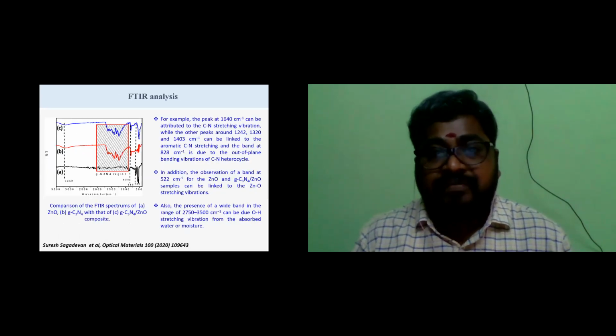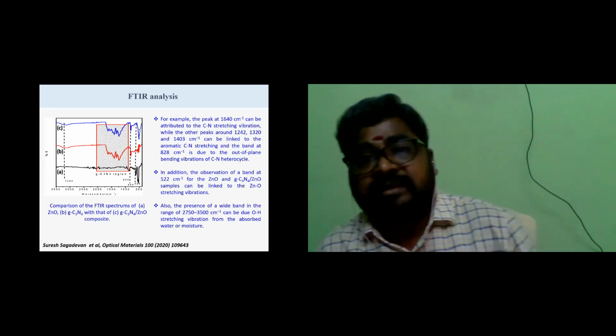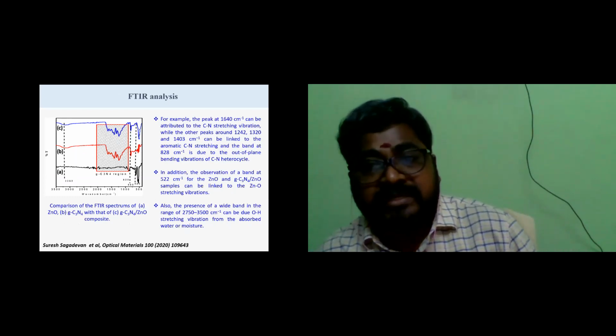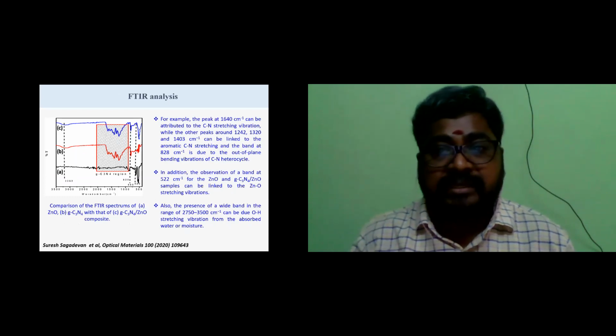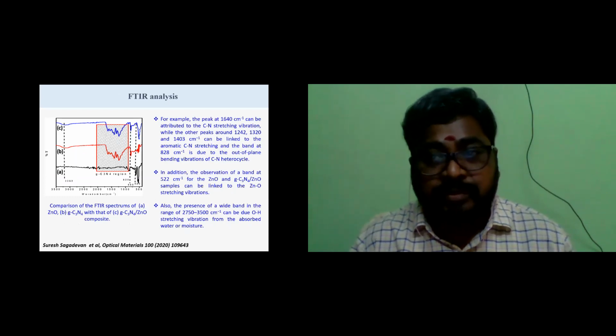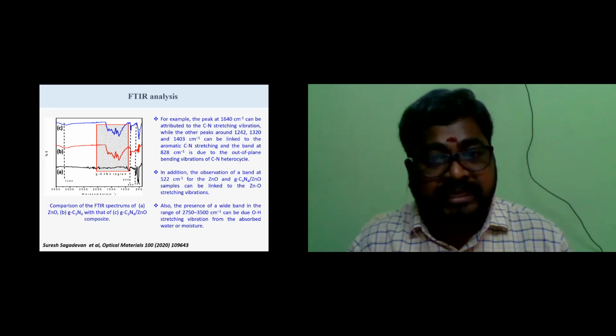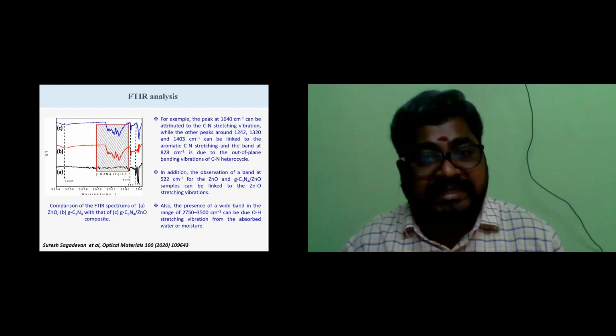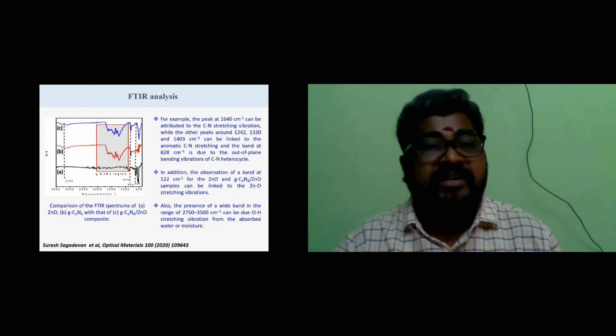And then in the FTIR analysis, once again we confirmed that carbon nitride consists of vibration peaks around 1242, 1320, and 1403 cm⁻¹, which can be linked to the aromatic C-N stretching.